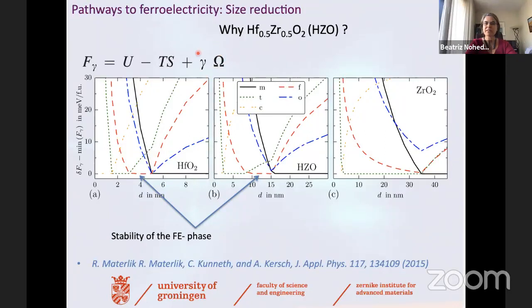As we just discussed, the surface contribution to the free energy is very important, and calculations demonstrated that in pure hafnia, this surface contribution can stabilize the ferroelectric phase, which is these red dashed lines here, between 3 nanometers and 5 nanometers. So you can see how tricky all this is. You really have to be at a particular size to stabilize this ferroelectric phase. And these people at NAMLAB were lucky enough to actually get in there. Of course, if you put in some dopants and you put some pressure during capping, you can elongate this stability a little bit more. And this is probably what happened to them too.